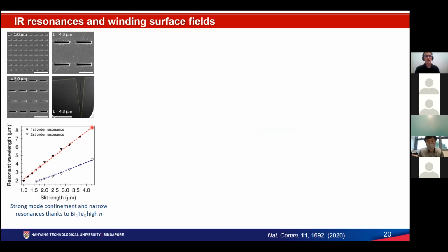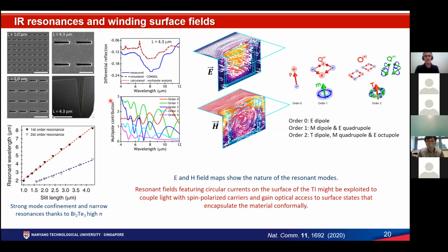And this supports a quite strong modulation, given by the fact that in the infrared, especially, you have a quite high refractive index. What we expected to be just a simple dipolar resonance actually turned out to be a very complex resonance. You have multiple, many orders of multipoles that are engaged in the resonance. And what we observed from simulation, of course, is that the resonant fields have circulating currents on the surface that appear. This could potentially be employed to couple with the spin polarized carriers that I mentioned just before.